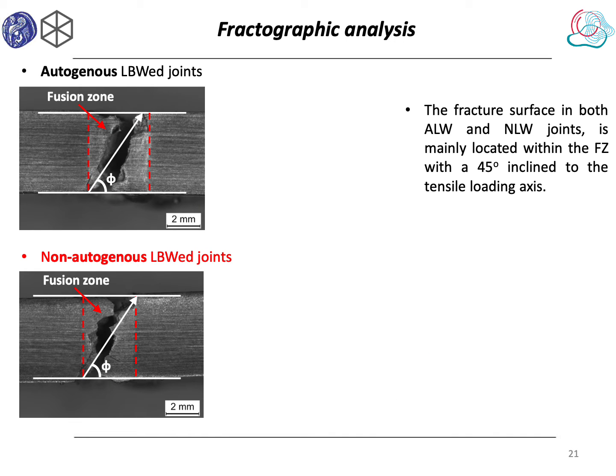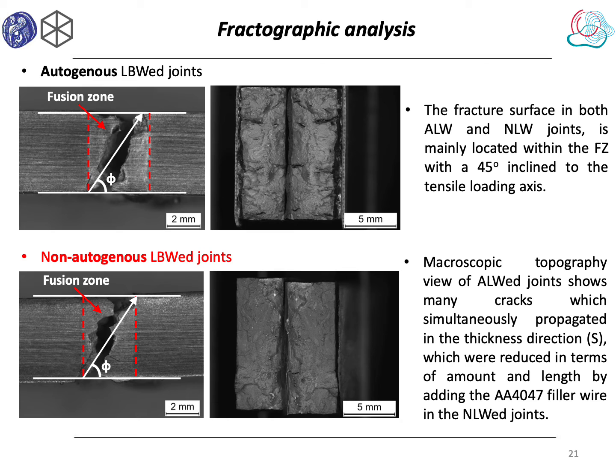The fracture surface in the laser beam welded aluminum alloy 2198 joints, for both autogenous and non-autogenous welds, is mainly located within the fusion zone with a 45 degree inclination to the tensile loading axis. This fracture behavior is independent of whether the welded joints were produced autogenously or using filler material. Nevertheless, the overall macroscopic topography of autogenous joints shows many cracks which simultaneously propagated in the thickness direction, which were reduced in amount and length by adding the aluminum alloy 4047 filler wire in the non-autogenous welded joints.